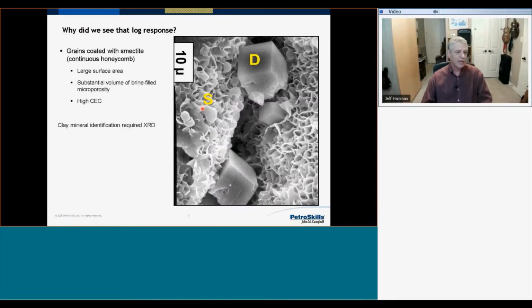Okay, so why did we see that log response for this Frio sandstone? The grains in this reservoir are coated with smectite, and that's what this honeycomb is. It is a swelling clay mineral. It has a large surface area, as you can see. All these blades in this honeycomb are a tremendous surface area, much of which would retain a brine coating, so there'd be a high water saturation associated with that porosity.